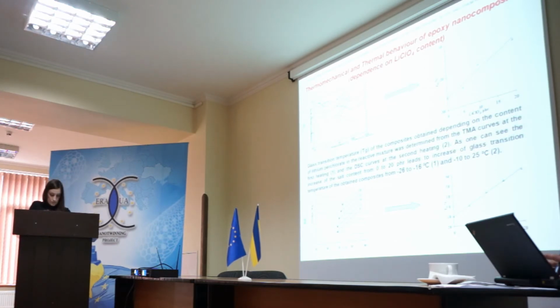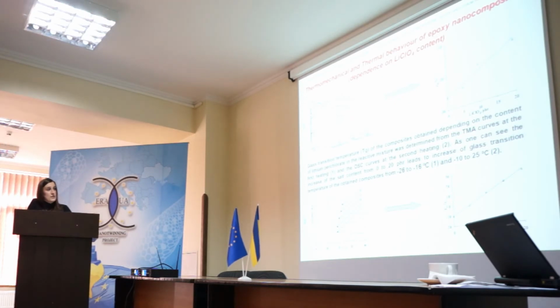On the other hand, the mechanical properties are also important for solid-state polymer electrolytes. It is obvious from the TMA results that addition of the salt enhances the mechanical characteristics of the nanocomposite. Also, the glass transition temperature of the composite, depending on the content of lithium perchlorate in the reactive mixture, was determined from the TMA curve at the first heating and the DSC curve at the second heating. As one can see, the increase of the salt content from 0 to 20 leads to an increase of glass transition temperature of the obtained composites.